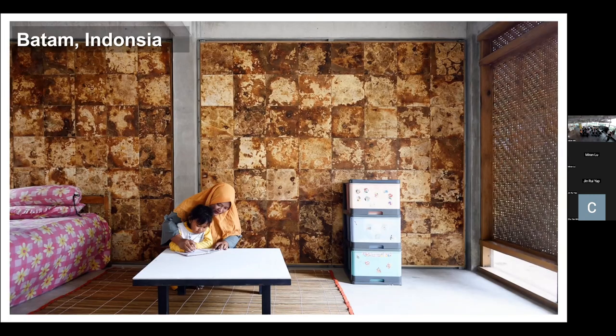Another project that we did is also part of the Batamos project, which Ali explained earlier about the bamboo. Together with our collaborators, we have also developed something like new wood, but not 100% similar to what we are working on at the moment, another version of the new wood, as an interior wall panel of the building. So we use mycelium only for interior applications because the material performs for indoor applications. It's not a 100% waterproof material, so we cannot use it to be exposed to the constant rain and humidity outside, but this was the interior of the building. It's not an air conditioned room, it's open space, but it's not exposed to, for example, rain.